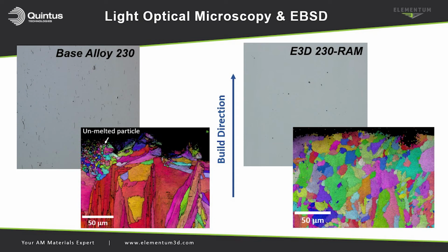If we take a step back and look at the resulting microstructure, right, the porosity, the defects internal to the material, as well as the grain size, grain morphology, what kind of learnings did you gather there? I think the microstructure really tells a great story all on its own. When you look at the alloy 230, you see extensive microcracking, vertically oriented in the growth direction. That's from the solidification cracking in that alloy. And with all that microcracking, you can tell that that material, without modification through the RAM process and without HIPping, it's not going to perform well. It's not going to be reliable, especially in fatigue type situations.